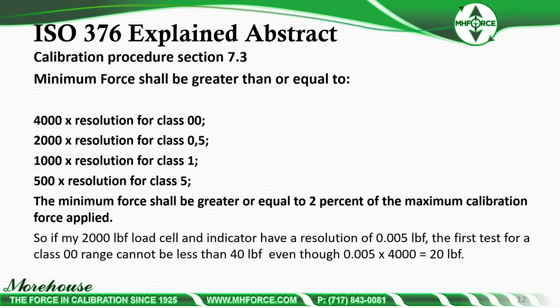Some other things about ISO 376, minimum force. ISO 376 uses a class system. ASTM has 2 things. If you're familiar with ASTM, they have class AA and class A ranges. ISO has 4 ranges, and these ranges are based on multiples of the resolution. The minimum force shall be greater than or equal to 4,000 times the resolution for class 00, 2,000 for class 0.5, 1,000 for class 1, 500 for class.